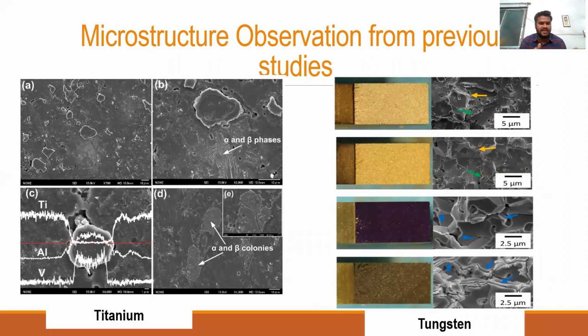Then the microstructure was observed from the previous study. In the titanium, you can see alpha and beta colonies formed, and in tungsten, the yellow and blue arrows indicate that grain growth occurred. So when the temperature exceeds a certain level in both these metals, grain growth is observed. So this was the gap I found, and I wanted to avoid this grain growth.